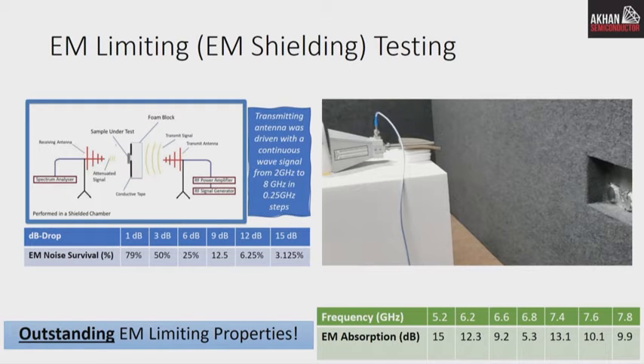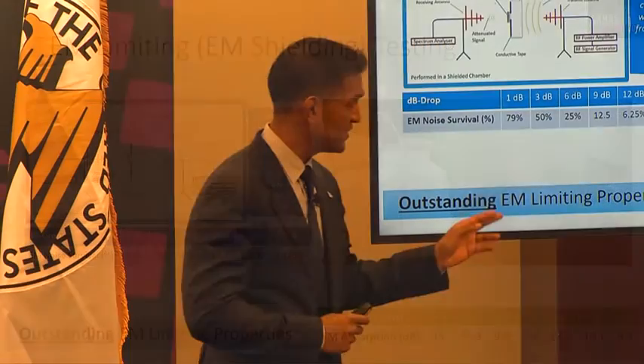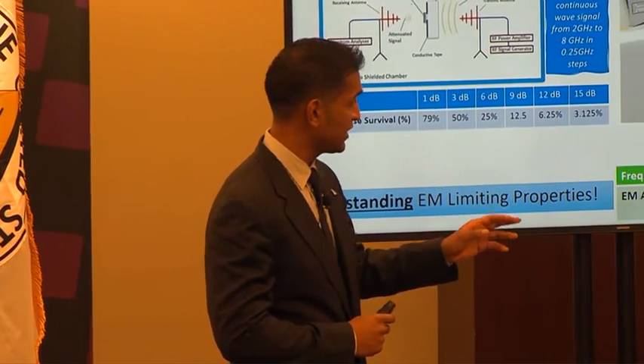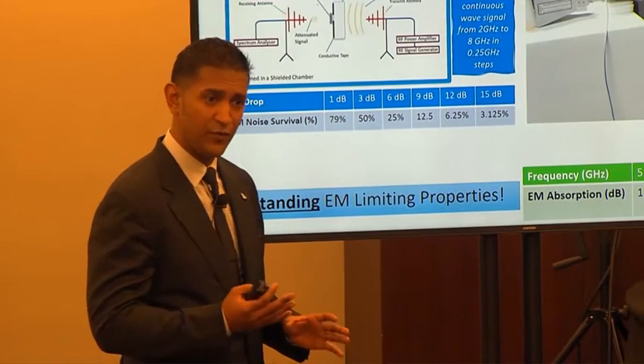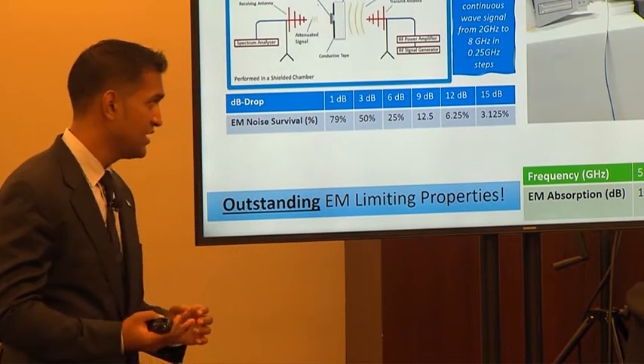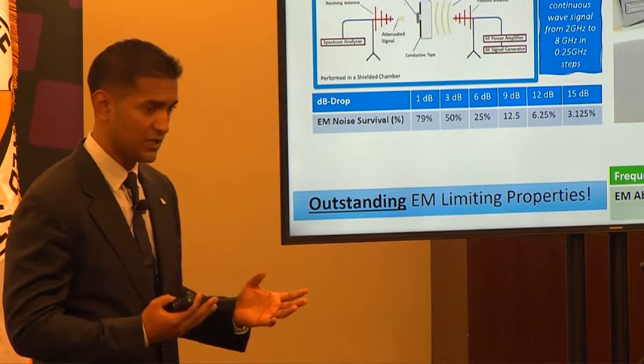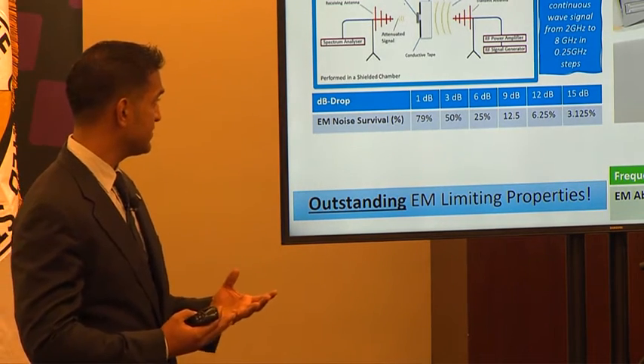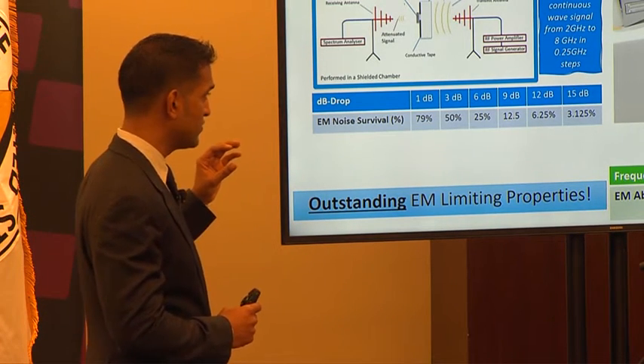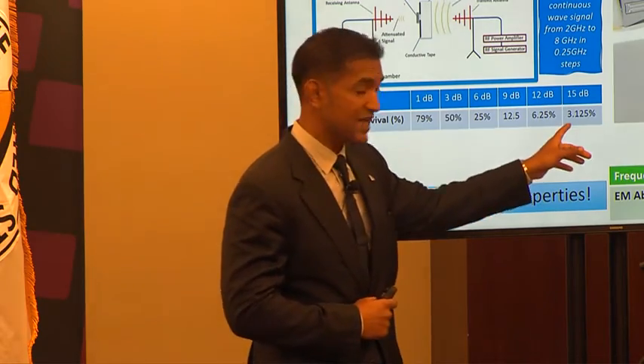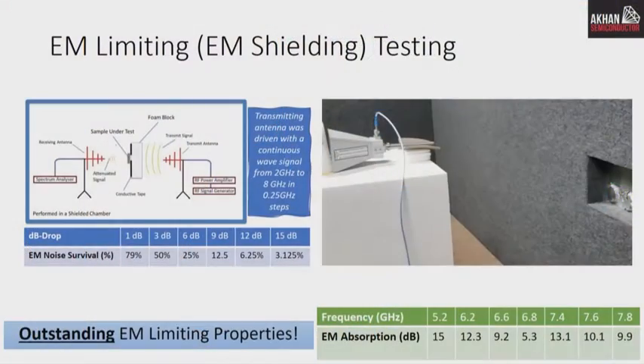We saw some pretty outstanding EM limiting performance from these parts, particularly between 5 and 8 gigahertz. We saw on the low end about 5.3 dB isolation or absorption, all the way up to about 15 dB absorption. To characterize that, it means that incoming noise will be reduced at 15 dB down to 3%. So roughly 97% of that signal noise that's being targeted towards the craft will be absorbed by this material. So highly, highly conducive from the EM shielding aspects.